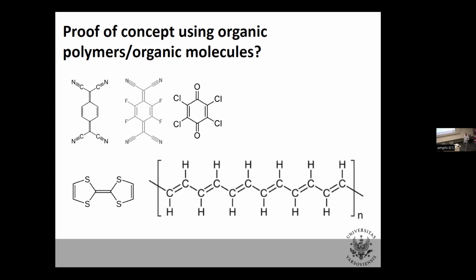So, in order to do this, you must have organic molecules that will fulfill this condition, that the valence band of one of them, the reducing agent, will overlap with the conduction band of the other, the oxidizer. Therefore, it's best if you use strong organic oxidizers and strong organic reducing agents. And of course, there are systems like this, TTF, chloranil, everything that is known, they form so-called charge transfer organic salts, right? These are beautiful experiments also from the late 80s, and this is a huge field. But in these salts, they either form segregated stacks, they are very close to each other, no separator, or they form alternating stacks, so they really touch each other.